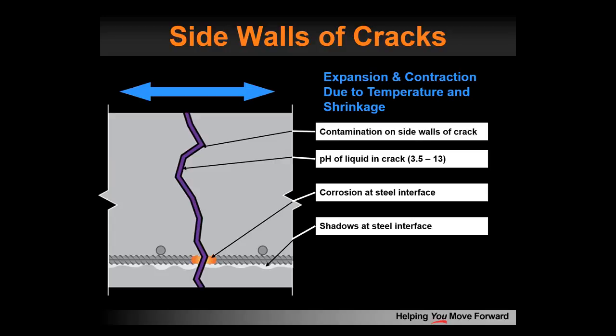it's not going to be 100% solution. Another thing that's also very important, and we'll talk a little bit later, is the pH of the liquid in the crack. There are many types of grouts that are not very resistant to super high pH environments, i.e. many times urethane type technologies. And in conditions where you have very high pH environments, typically we're looking at acrylamides and acrylates. Sometimes corrosion of steel byproducts are in the crack, and that can be difficult.